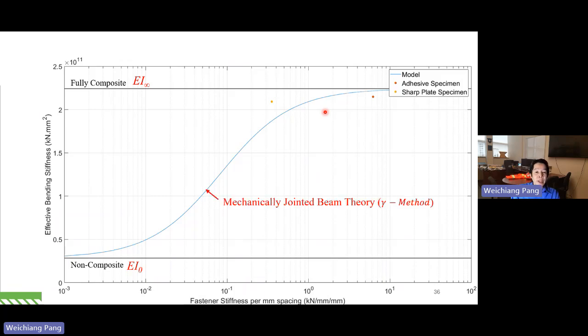And then based on our test, right? Before we get to the test, we can actually use the mechanically jointed beam theory, varying the stiffness of our connector, to come up with this curve here, right? The composite curve here. The horizontal axis shows the stiffness of the connector per spacing, in kilonewton per millimeter, and then per millimeter of length here. From the test, sharp plate achieves about 93% based on here, right?